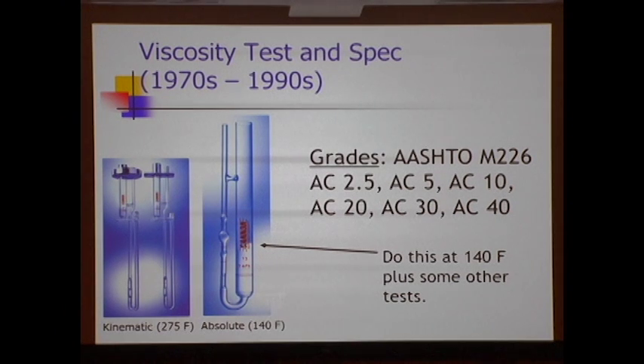The main, and Darren, I think, showed a good picture of this. You load about 30 grams or so of asphalt in a tube. You measure the amount of time it takes to flow between a couple of calibration marks, and that gives you what the viscosity of the asphalt is. And you do that at a number of different temperatures. So immediately, you're better off with this because you're more thoroughly characterizing asphalt at a wider range of temperatures.